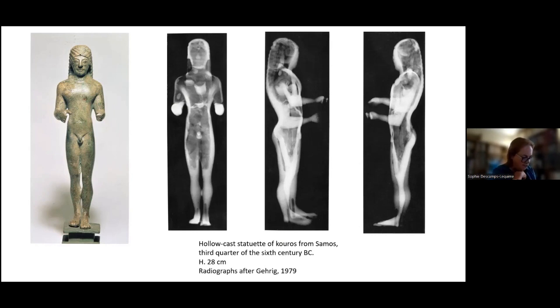The legs, feet, forearms, hands, and sex are full wax models, which were added to the body. The head was obtained from two halves. The craftsman used a bivalve mold from the front and back of the body, from the neck to the knees and elbows. Profile X-rays of the body reveal two almost vertical lines in the core, one lighter, the other darker, converging at navel level and corresponding to the mold's suture.